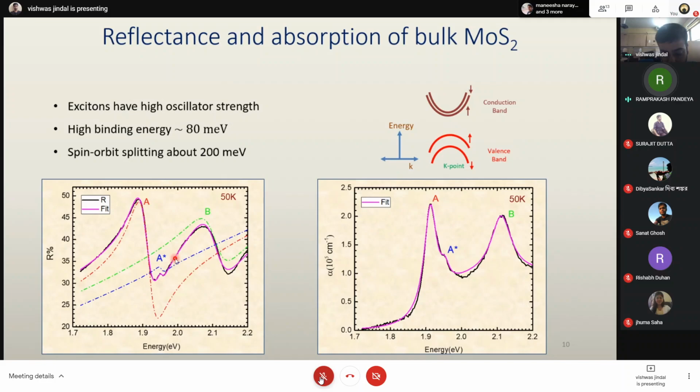The band gap usually increases as you go down in temperature, because the lattice vibrations are going down. There is some broadening associated with the conduction and valence bands, which tends to reduce, so they become sharper as you go down in temperature.